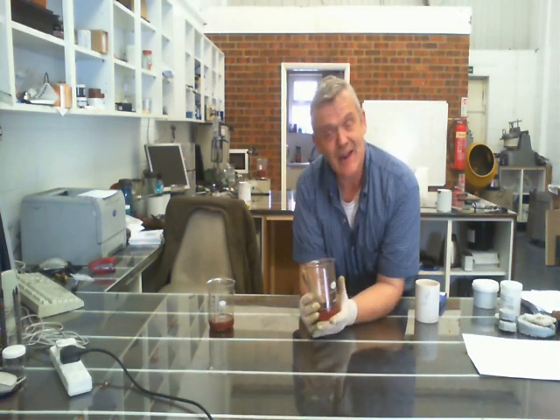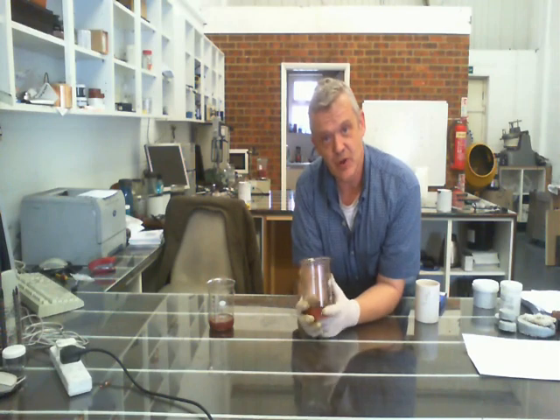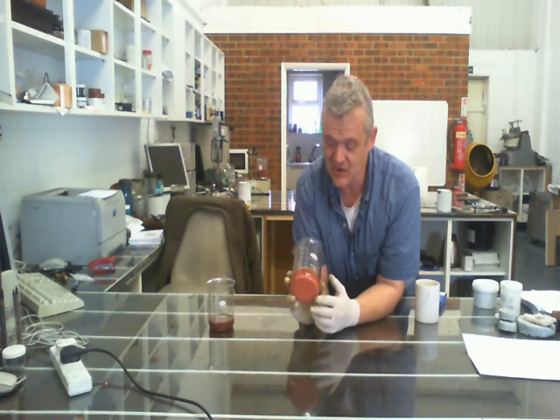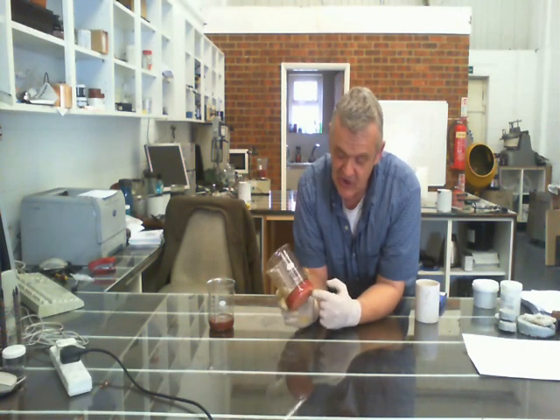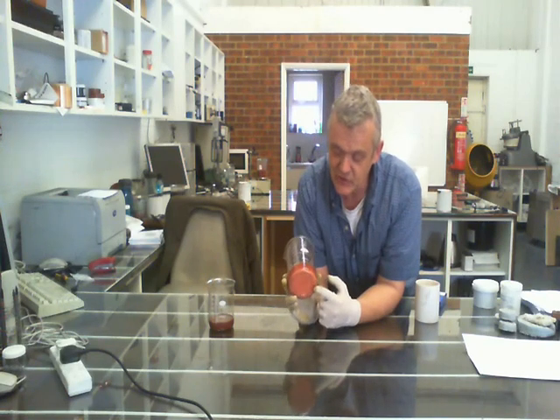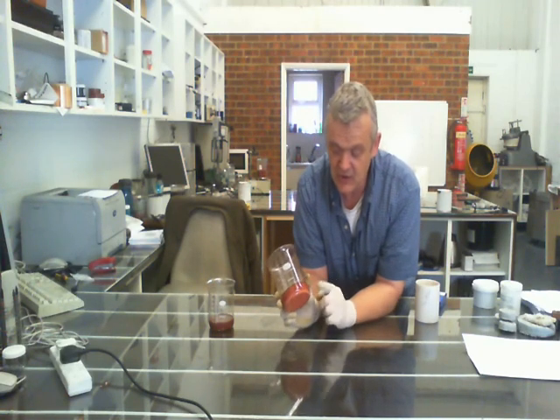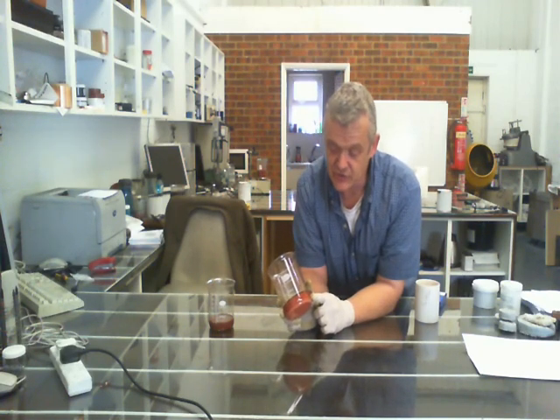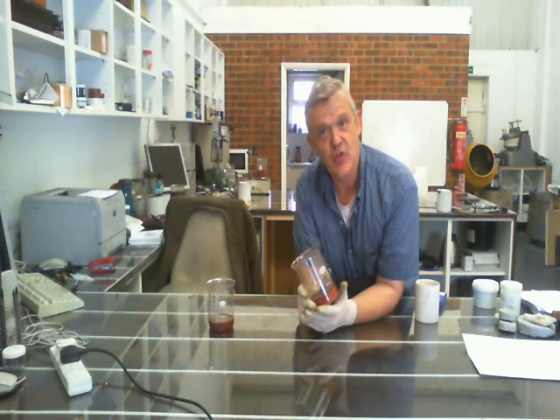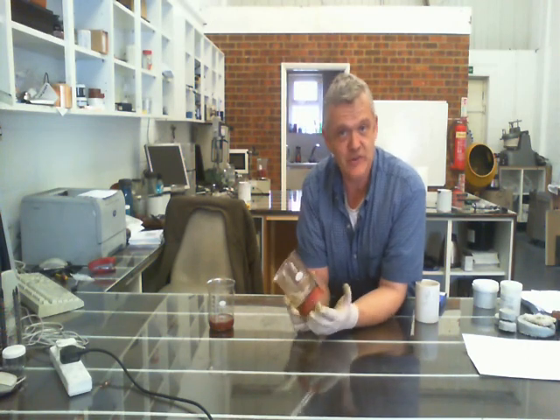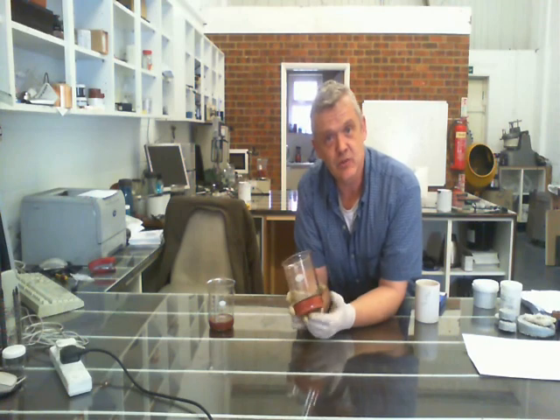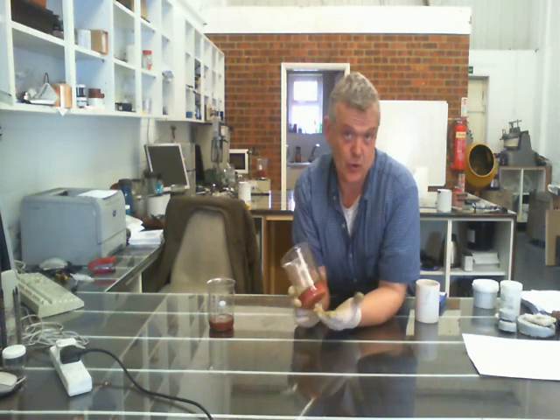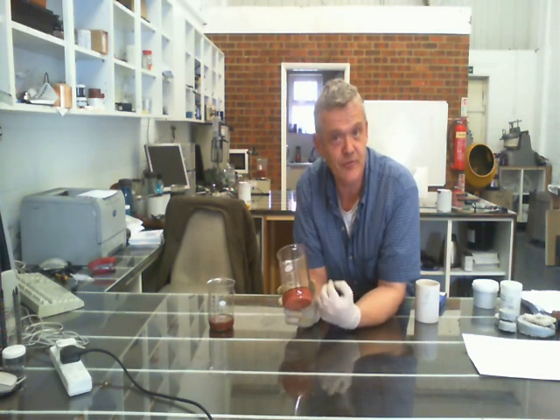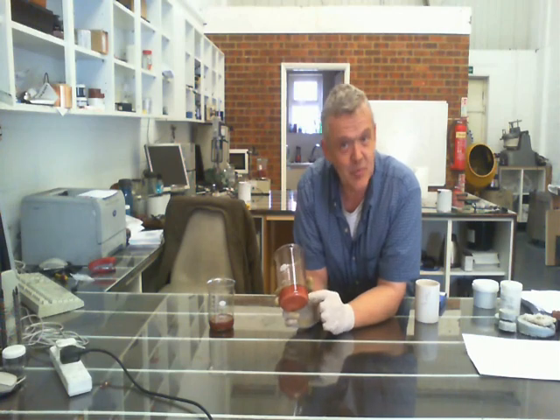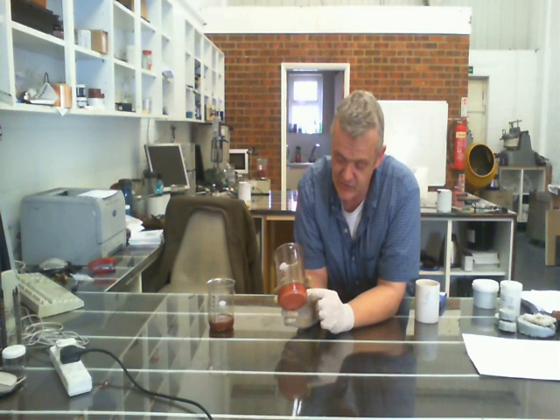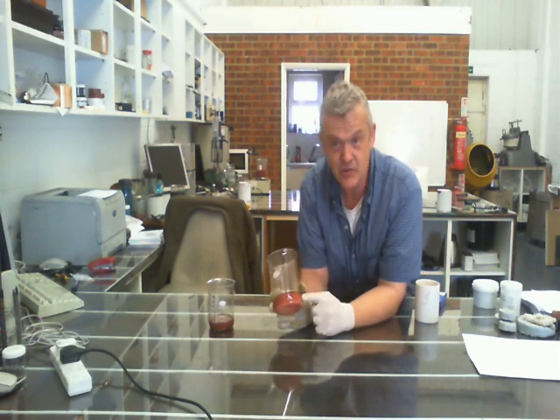Now, as I say, you can add other things to that once you've done. There's no reason just to leave it as that jelly, because that jelly is not oxygen safe. That will oxidize and the copper will turn back to copper oxide. So you need to put an oxygen scavenger in there. Now, lots of things work as an oxygen scavenger. Sodium sulfite, sodium thiosulfate, ascorbic acid, all of those things will take up the free oxygen and help keep that as copper nanoparticles until you're ready to turn it into an ink and sinter it.